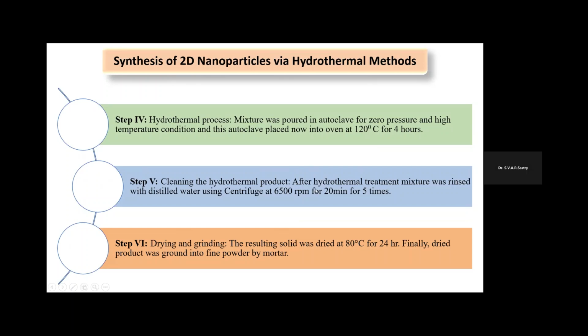Then at the end, we took out the product from the hydrothermal synthesis, then centrifuged at 6500 RPM for a period of 20 minutes, 5 times. Then we did drying and grinding at a temperature of 80 degrees Celsius for 24 hours. And finally, we got the finished product.